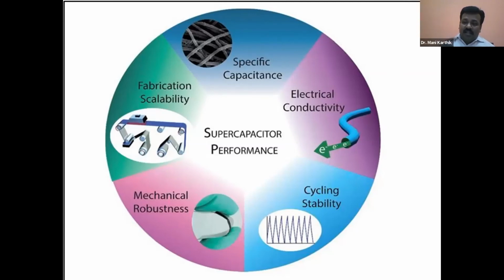Then cycle stability. Cycle stability depends on several parameters. As I said, it should be a resistance-free cell. Then only can you get a very good high performance material, and the pore size and the ionic size should be matched. Then only can you get very long cyclability. And mechanical robustness, because some people are working on flexible electrodes. Also some people are working on coated electrodes, which have very good adhesion between the electrode and the current collector, so it does not peel off from the current collector. That is very important. And of course the fabrication of cells. These are all very important for supercapacitor performance in commercial level tests.